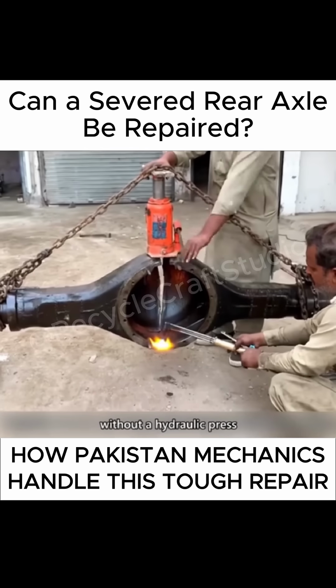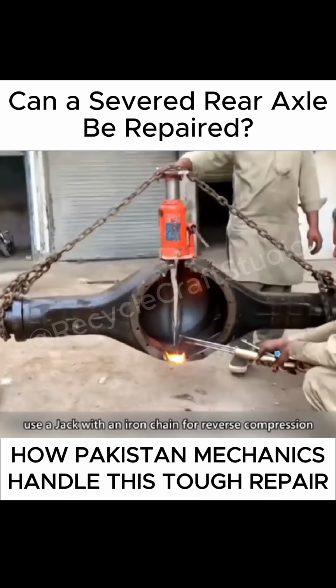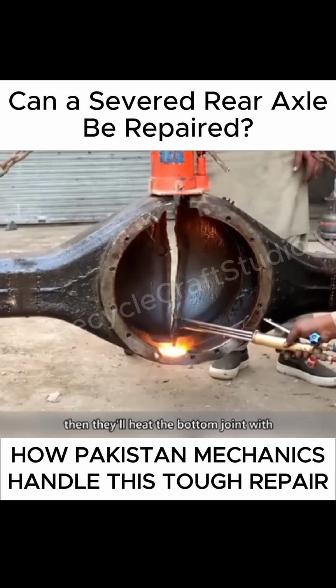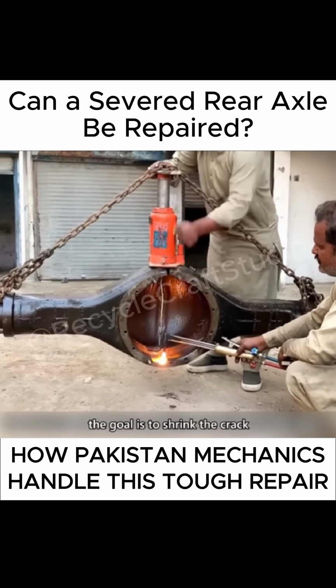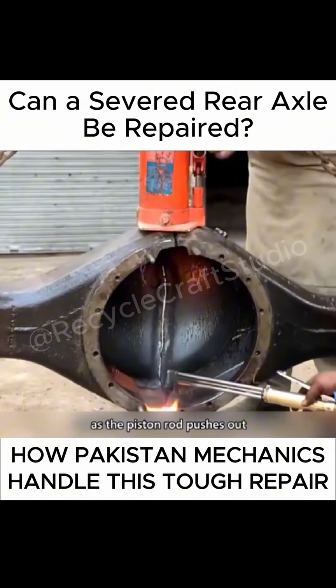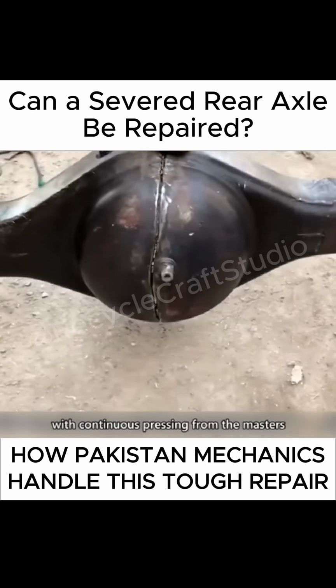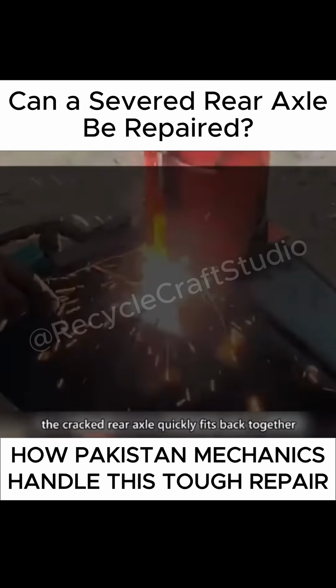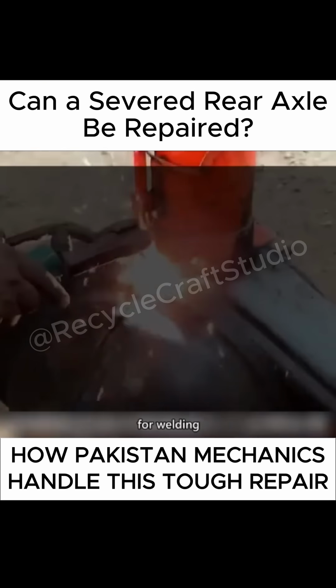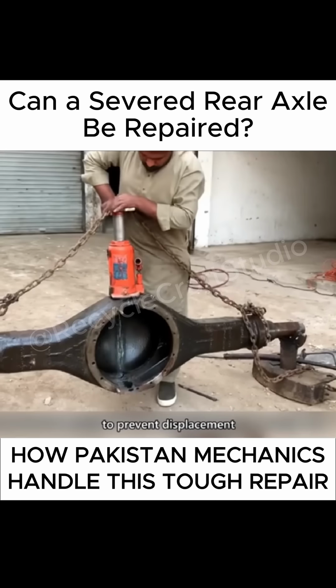Without a hydraulic press, they plan to use a jack with an iron chain for reverse compression. Then, they'll heat the bottom joint with acetylene to anneal the steel plate. The goal is to shrink the crack as the piston rod pushes out. With continuous pressing from the masters, the cracked rear axle quickly fits back together. To prepare for the disassembly of the jack for welding, the masters first spot weld the crack to prevent displacement.